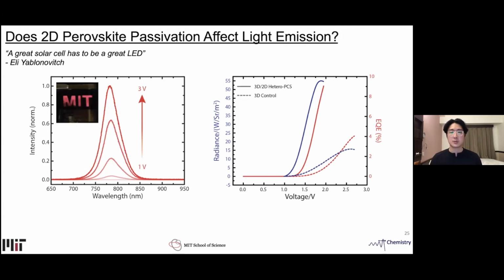On the right, I'm showing a curve of radiance, which is how bright it is, and EQE, which is the electroluminescence efficiency, versus voltage. Here, the dotted line is the 3D control and the solid line is the 3D/2D heterostructure. We see about a threefold improvement in the EL efficiency and also brightness for the heterostructure compared to the 3D control.